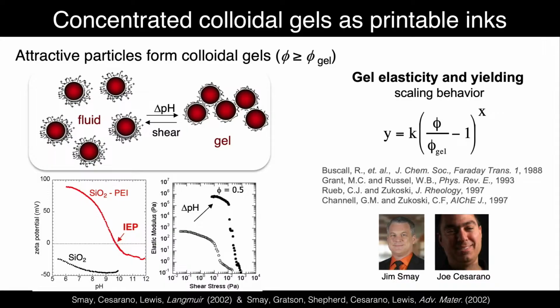And the idea here is to take colloidal particles. In this case, we're working with silica. And in the absence of any kind of surface coating, silica is a negatively charged particle over a broad pH range. Its isoelectric point is actually a pH of 2. When we functionalize this with polyethylenimine, which is an oppositely charged cationic polymer, these particles become very highly stabilized. We can go to high volume fractions, which allow us to engineer and build in a stiffness, an elastic modulus that allows them to be spanning.